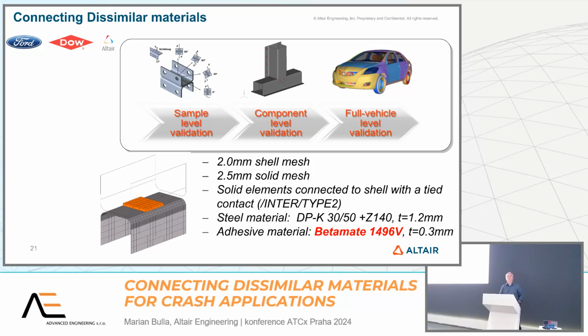We did it also with Dow, Betamate, and connected this peeling layer, the adhesive layer, which is here, to both surfaces mesh independent, using a tight contact interface, which is very nice and works pretty fine. If you bond adhesive between two plain metals, without any coating, without any paint on it, which is for testing the adhesive, it's perfect. For reality, we will see.